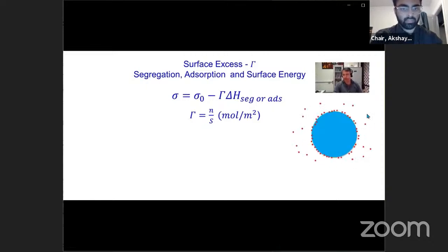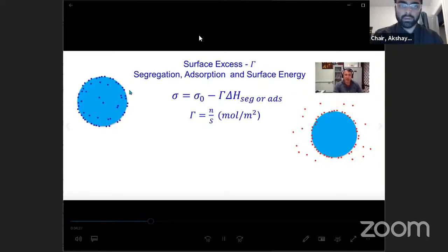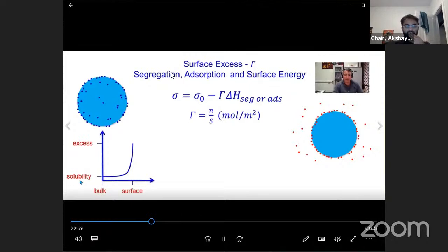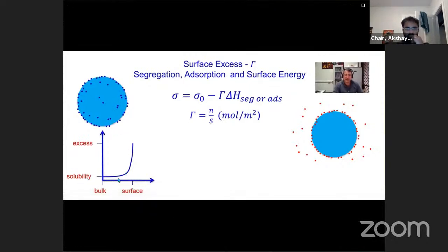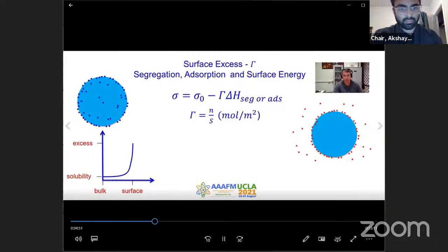Then with the gas, we have the pressure of gas, and next to the surface we have an adsorption layer, and this adsorption layer determines the surface excess, and then you have a decrease of surface energy. It's the same case for segregation. When we have a solid solution, in the bulk we have the solubility, but next to the surface we have an increase of concentration. This increase of concentration is the surface excess.